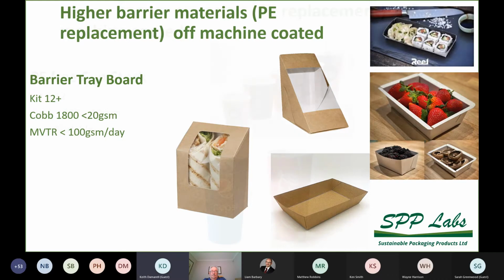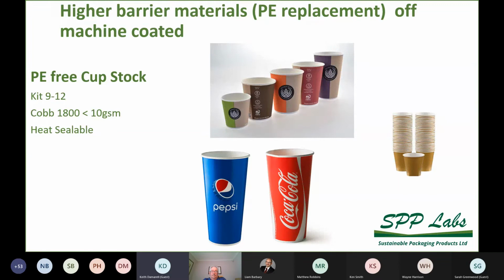If you move on to the next slide, one that I think will be very familiar to most people is beverage cups. It's true to say today there are several board mills with off-machine coating operations and one with on-machine that are today offering barrier-coated cup stock for the production of beverage cups. It's quite technically challenging because you need even greater liquid water barrier. For a cold beverage cup, it needs to hold water for at least 4 hours, and for a hot coffee cup, at least 30 minutes. But the material also must have very good heat seal properties to run well on a modern cup forming machine.